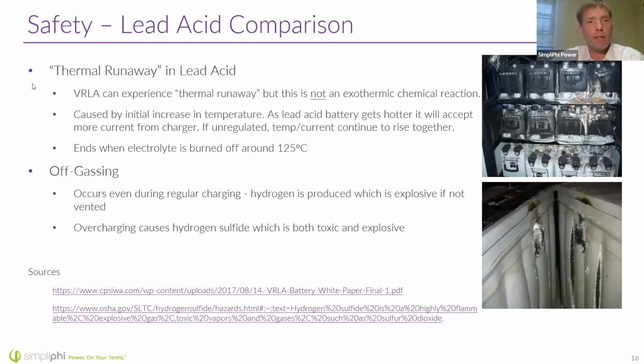Okay, can lead acid batteries go into thermal runaway? Well, lead acid batteries are a bit different from lithium ion batteries. We don't need to spend a lot of time on this because most people are not using lead acid batteries anymore, but there are problems with deep cycle lead acid batteries, right? And one of those is that these batteries can get hot. If you charge a lead acid battery too quickly, what will happen inside is that as you increase the temperature, the battery will accept energy more rapidly, right? And because it's accepting energy more rapidly, the battery can get hotter and hotter.